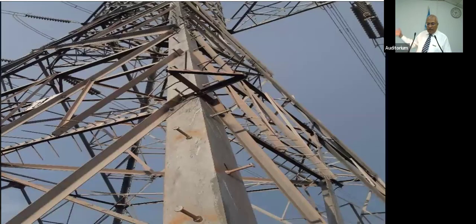Now this one is a wind power project in the Mannar area, by the electricity board. They have the wind turbines and transmission galvanized towers going to Anuradhapura through the jungle. Most of the part is in the seaside area, C5M, with sea breeze on the galvanizing, already corroded. It's not the galvanizer's issue. They should have duplex coated it. If it is C4, C5M, you have to go for duplex coating. But they didn't do it.